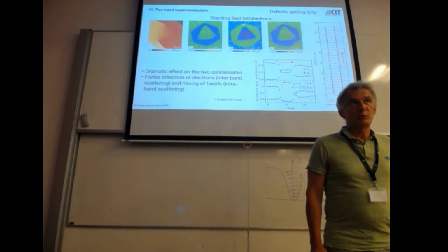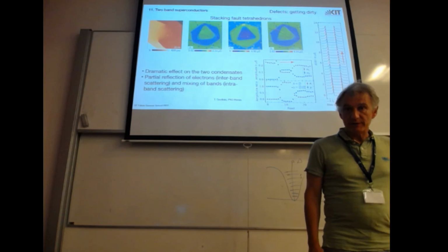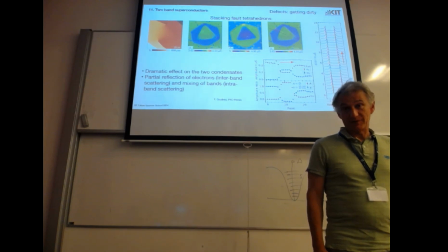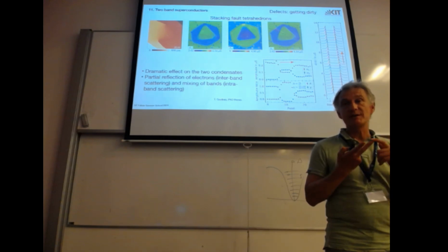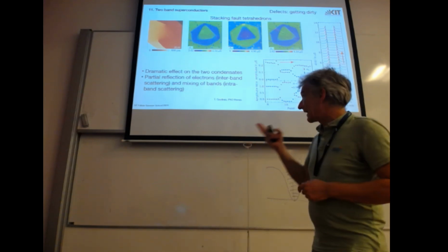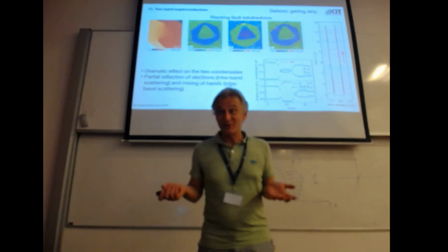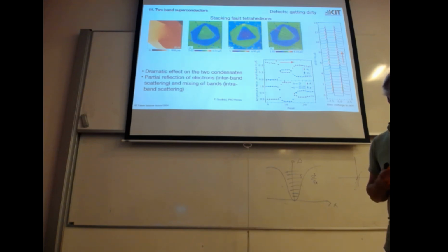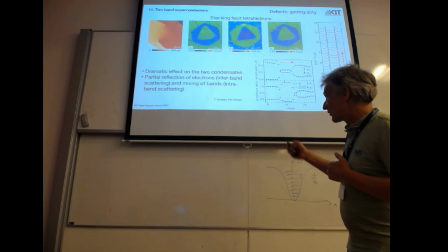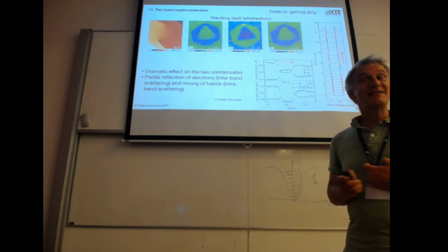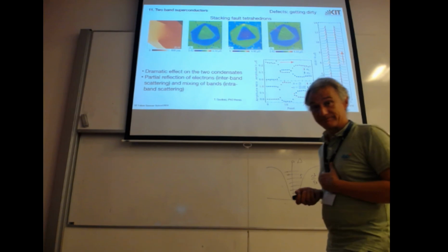There are conventional superconductors, magnesium diboride is one example, where only one band couples to the phonon, the other not. But both have interband scattering. And in principle, you have two Eliashberg functions. You're right. For every band, there should be an Eliashberg function. Interband coupling will couple these equations. These are so complicated, I think no one actually did this. Because what you showed looked precisely like a one-band function. So in my Eliashberg work, I neglected that there are two bands. Correct. And this is a simplification.